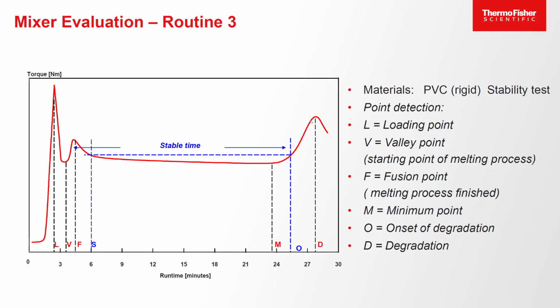But these additives, these stabilizers, have a certain capacity. After a while, they are saturated and not able anymore to stabilize the PVC. And that's what we see here at the end of the curve. Here, our stabilizers are saturated, and now the PVC degradation starts. You don't want to have this degradation in your production machine. Here, HCl is produced. Here, the material turns from an easy to clean material to a nasty, sticky, corrosive black mass, which can even pollute the next extrusion. So you really don't want this to happen in production.